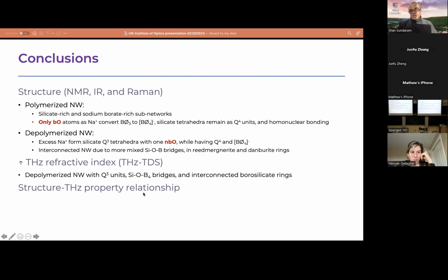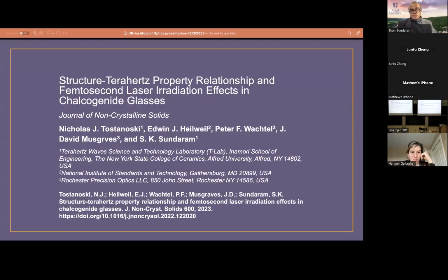And we clearly see the terahertz refractive index varying almost linearly with the R values, which correspond to the glass chemistry. So this is one way of putting together a structure-terahertz property relationship for a family of glass. We have to do this for every family. Once we put together some of these families, then we can afford to extrapolate or interpolate this data, and we may be able to predict, if I select this composition or add certain additives to the glass, what kind of terahertz properties I will be able to get in this system.